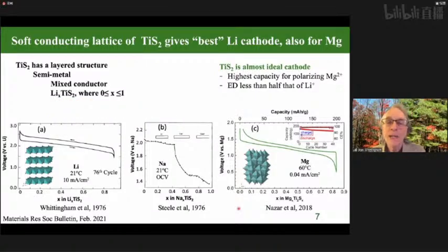So we had TiS2. The big advantage of it is what we call a soft conducting lattice. In other words, it's a metallic conductor, covalent bonding. So ions can diffuse very readily in it, and you do not need to add any conductive additives, such as carbon black. And you can see on the left-hand side, the example of lithium. And this is at 10 milliamps per square centimeter. Remember that number for the moment. This is the 76th cycle. And the difference between a charge and discharge curve is just the resistive losses in the electrolyte.